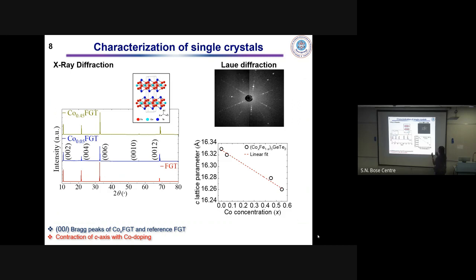And from the structural refinement, we could see that there is a decrement in the lattice parameter C as we were increasing the cobalt concentration.